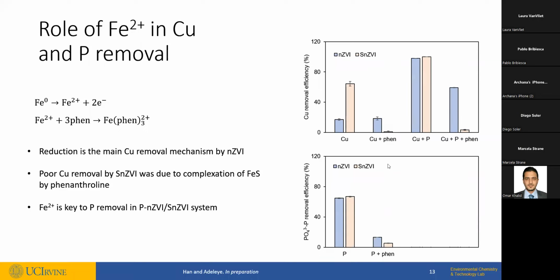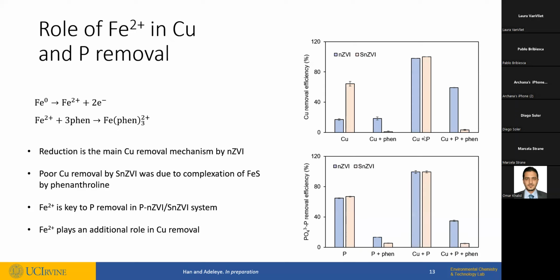Now, when we now mix the 3 components, which is copper, phosphate, and the nanoparticles, here you see the remarkable increase in performance like we saw in the data I showed earlier. However, when phenanthroline is present in that system, the performance of NZVI decreases somewhat, which tells us there may be some contribution of Fe2+ to the removal of copper. But again, SNZVI is just not working because its entire surface is covered by phenanthroline. And the story is similar for phosphates.